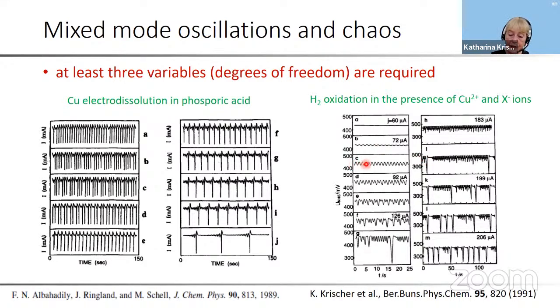And here you see that we have simple periodic oscillations. And as we change the applied current density, these are galvanostatic oscillations, you get a period 2 oscillation, and here a period 4. If you look, there are 2 different levels of the larger oscillations and 2 different levels of the smaller ones, and they finally become irregular. So this is an example of a period doubling cascade, and this usually ends in chaotic dynamics. And also here, the dynamics might then even become more complex, and the chaotic small amplitude oscillations might be interrupted by large excursions, as shown in the remainder of the time series.